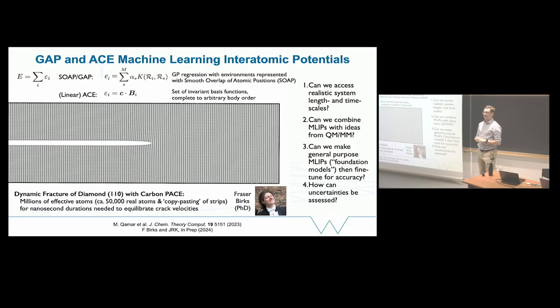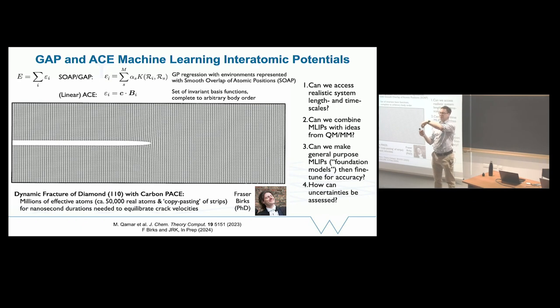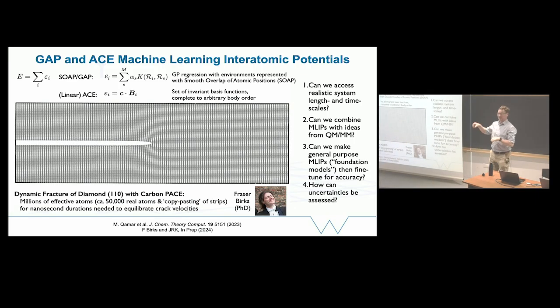Is this model realistic? It's realistic because above the critical load, cracks, the barriers are all 0. So all the bonds do break more or less at the same time. And the crack front advances as a battalion rather than as an individual soldier. But it depends on the specific setup whether that's valid or not. If you were looking at an impurity, that would be a problem because you'd have an array of impurities that were very close to one another. That might not be physically reasonable. So. Yep. Short question.